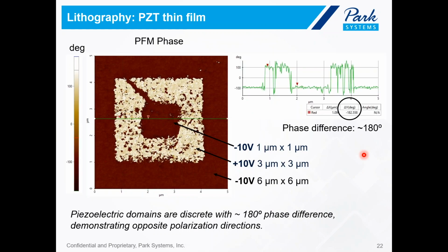So here, I'm going to show you a very similar but different example. Here, what I did is we first scanned a region that is 6 micron by 6 micron, so the largest region, with negative 10 volt DC bias applied to the tip. And then we scanned a 3 by 3 micron region with positive 10 volt DC bias applied to the tip. And finally, in the center, we scanned a 1 by 1 micron scan with, again, negative 10 volt tip bias.